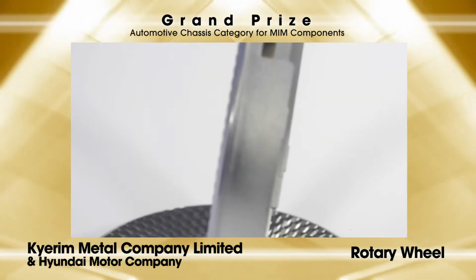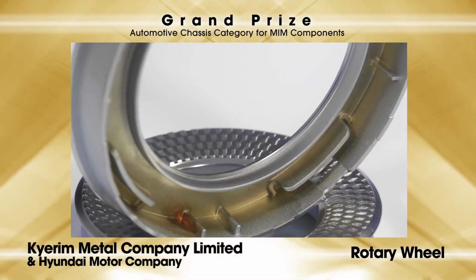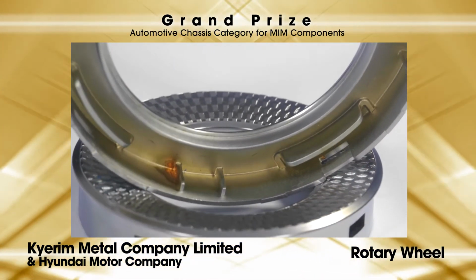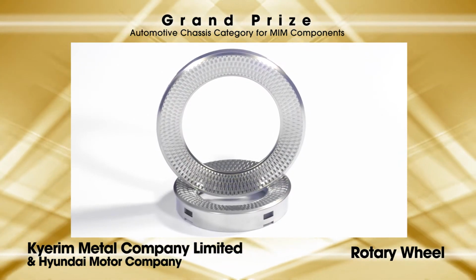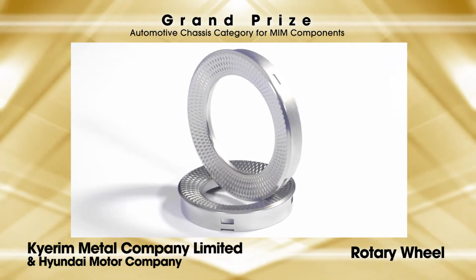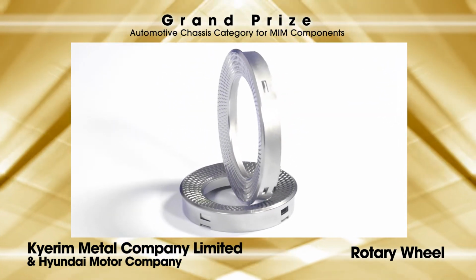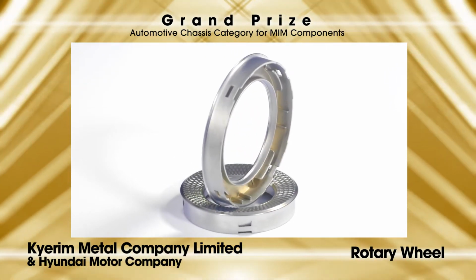4 fan-shaped gates were used, equal to the number of side cores. The gas generated where the feedstocks met was vented to each slide core to control possible injection defects. Overblocks in the inner part of the cavity improved the flow mark, prevented defects, and acted as ejection panels. A plus or minus 0.1 mm roundness and flatness requirement was met without secondary operations.